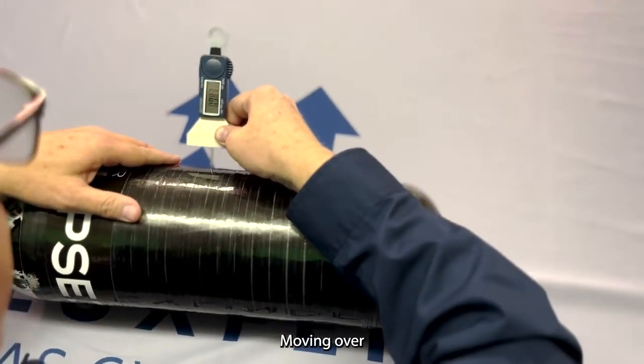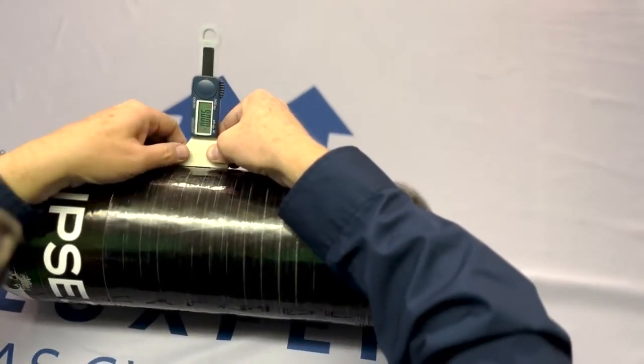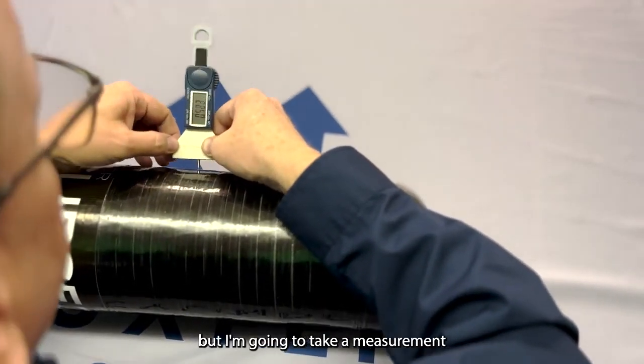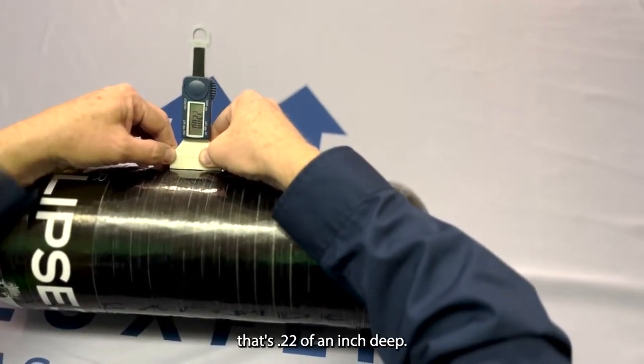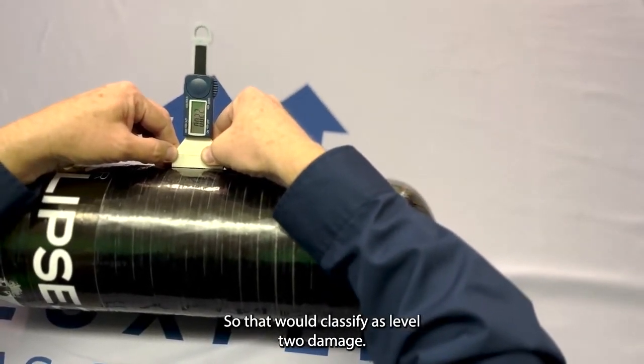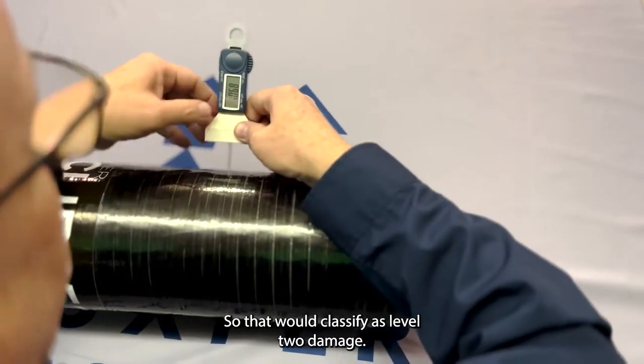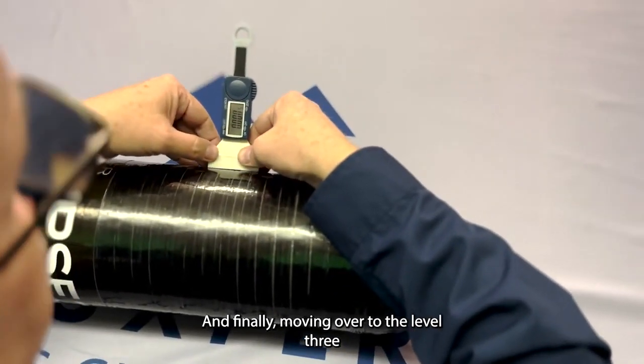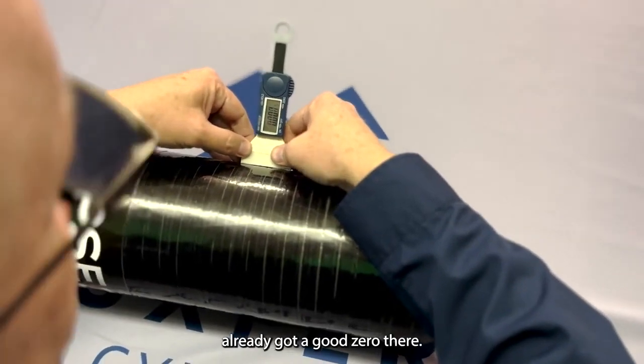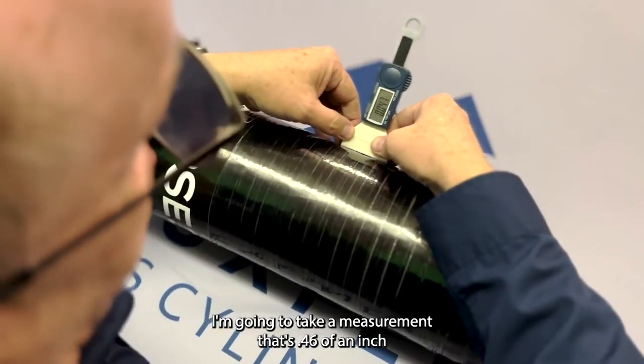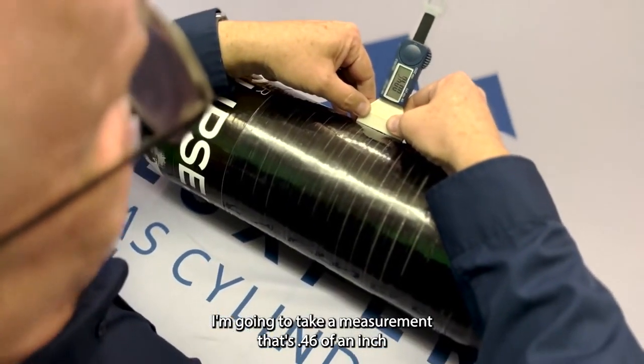Moving over, again, I'm going to zero that out right next to the cut. And I'm going to take a measurement. That's 0.22 of an inch deep. So that would classify as level 2 damage. And finally, moving over to the level 3, I've already got a good zero there. I'm going to take a measurement. That's 46 thousandths of an inch.